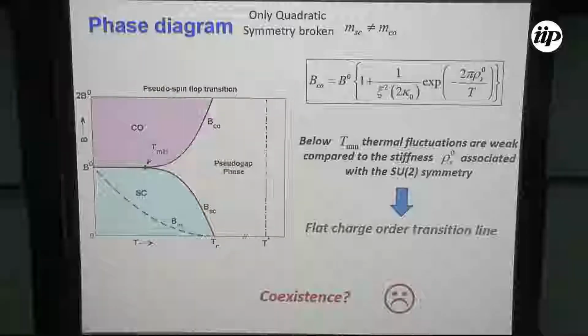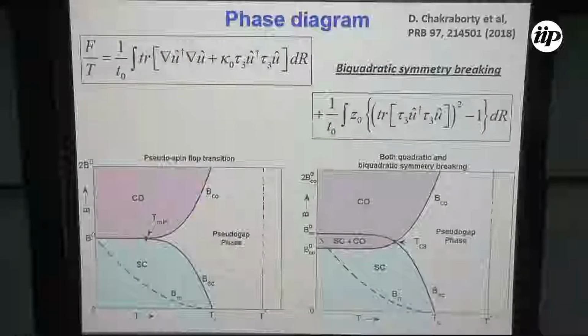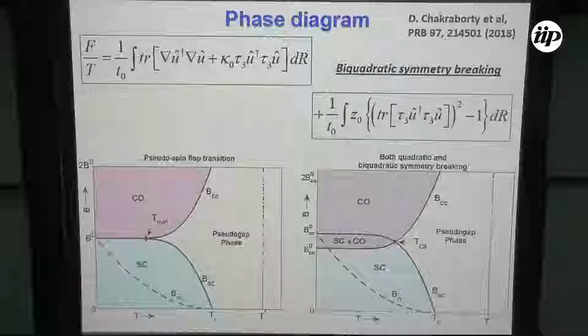So we are happy, we are partially happy because we have obtained the flatness, but we have not got the coexistence, because I was showing you that in experiments, we need a coexistence phase at low temperature. In order to achieve the coexistence, we have to break a higher order symmetry. So I showed you the BT phase diagram for this part only, which was this, where there is no coexistence. If we need a coexistence, we need to break a higher order.